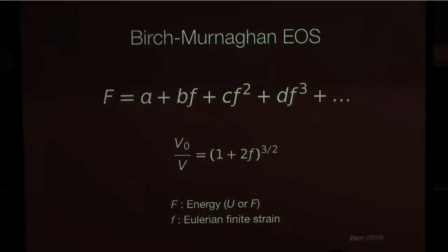So now, there's a problem if you do it this way. What's the problem? If f goes above 1, or if the higher order terms of f are not sufficiently small, it matters where you make the truncation. That's really important.